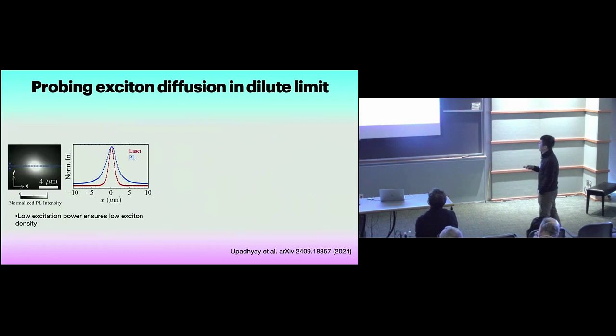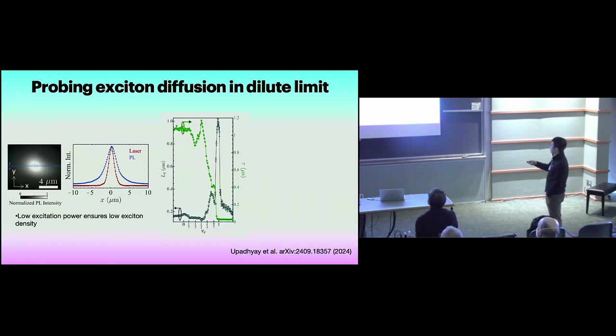And we vary the density of the electrons inside the system. So on the horizontal axis, I'm showing the filling factor as a function of gate voltage, and this is the diffusion length. So quite strikingly, initially in this empty lattice, the diffusion is small, but when we approach this electronic Mott insulator, there is a quite strong enhancement of the diffusion. This was quite counterintuitive initially for us because we would expect that in the electronic insulating state, the exciton diffusion should also be impeded. You may ask, maybe this is due to the lifetime of the exciton changing with gate voltage. So we also measured the lifetime, and we found that the lifetime actually decreases.